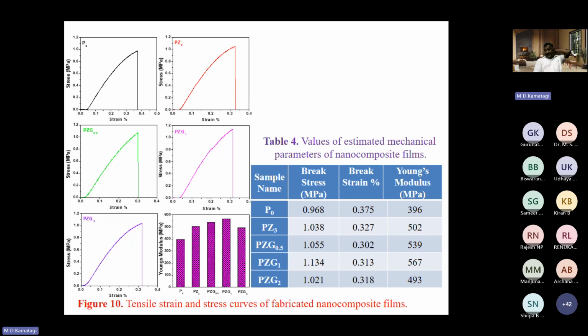Now we looked into the mechanical strength because we are doping with a very high mechanical strength material, that is graphene oxide. These are the values estimated, the mechanical parameters of the nanocomposite films. So P0, being a pure polymer, has a Young's modulus of 396 megapascal. Whereas this PZG1, this is the stress versus strain diagram. From this we have evaluated the Young's modulus. The PZG1 shows a very high Young's modulus. That means its breaking strain and breaking stress are more than any other composites.